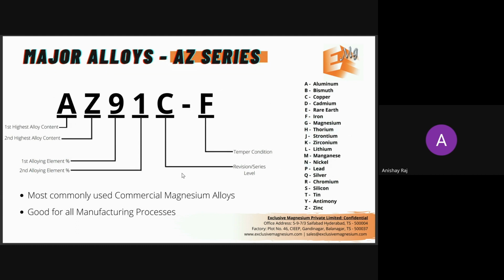You want to get into magnesium alloys and you want to understand what the alloy grades are. So I'll take you through three of the major series that come into conversations for any product. The first one, and the most commonly used commercial alloy, is the AZ series. It's nothing complicated. As you can see from the table on the right, A is aluminium and Z is zinc, right? So AZ, and then 9 and 1 correspond to the aluminium content, which is 9%, and zinc 1%. That's the composition, and the remaining is all magnesium. So that's about 90% magnesium, 9% aluminium, 1% zinc.